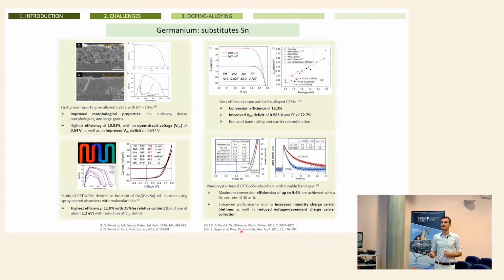Finally, for germanium, there are many works, and in all of them the efficiencies are normally very good. So when you start to substitute tin by germanium, up to 40% of substitution, you can achieve very nice efficiencies, more than 12%, quite easily, indicating once again that tin is a problematic material. Once again, germanium is a quite expensive and non-abundant element. So understanding the problems is very nice, but we always need to go back to tin, because tin is the really abundant element. So all this work is very useful for understanding the properties of the material, but not for industrialization in the future.